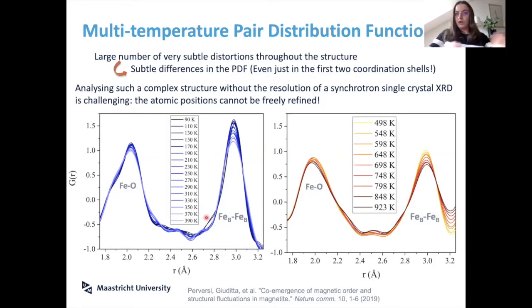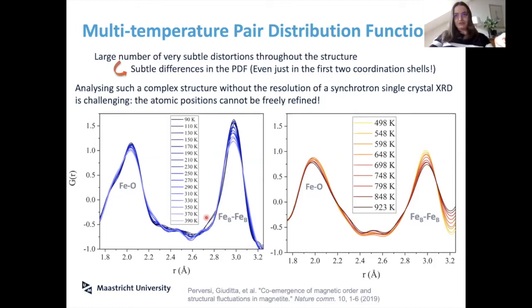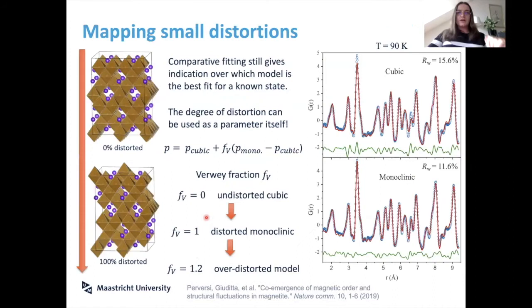Small deviations might be swallowed up by the thermal broadening of your distribution. This is a moment when using a single-crystal-derived model in a powder diffraction really clashes with the limits of the two techniques — you're using atomic positions refined by single crystal, which is excellent for precision, but a powder sample is not meant to give that resolution. You cannot freely refine atomic positions in this model: it won't make physical sense and your modeling program won't like it — too many variables, overfitting.